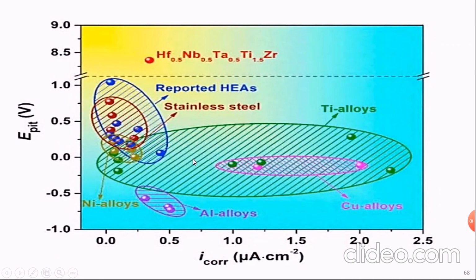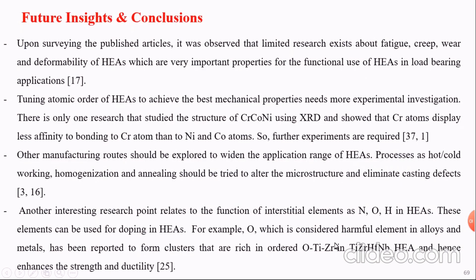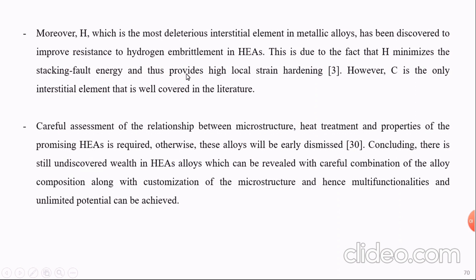Some other high entropy alloys were tested for corrosion resistant applications and proved good efficiency, better than nickel alloys and stainless steel. If we talk about the future insights of high entropy alloys, upon surveying the published articles, we found some points are missed. For example, very limited research is found on the fatigue, creep, wear, and deformability of high entropy alloys, which are very important properties, especially in load-bearing applications. Also, another interesting point is that no one revealed the role of interstitial elements like nitrogen, oxygen, and hydrogen in high entropy alloys, especially hydrogen, which causes hydrogen embrittlement in regular alloys. How can it behave in high entropy alloys?